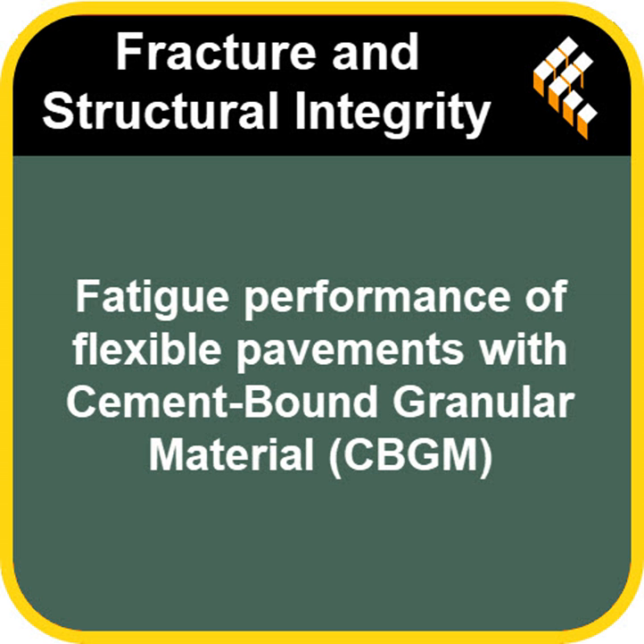Yes, much sooner. It's based on a formula using the tensile strength and the calculated tensile stress at the bottom of the layer, essentially, how much the layer is being pulled apart versus how much pulling it can take. For the calculations, Dempsey proposed assuming the tensile strength is only 1/5 of the compressive strength. So in this study, with a compressive strength of 2.4 MPa, the flexural strength, the strength against bending and cracking, was set at a very low 0.48 MPa.